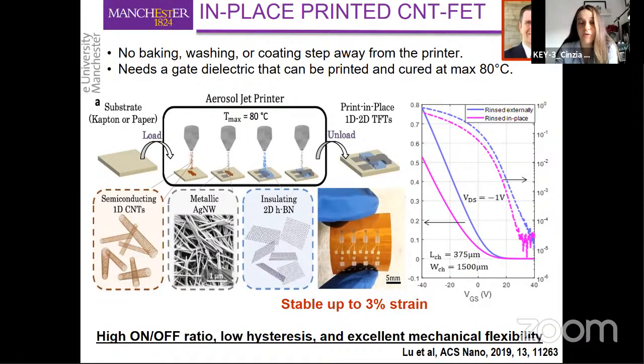And this is enabled by the use of materials that have very good performance even under such a low processing temperature. And this was a problem in the past for Aaron. He tried different types of dielectric materials, and they were always failing every time he was trying to produce the device in these limited conditions. But our boron nitride, in combination with the semiconducting carbon nanotubes and metallic nanowires, demonstrated the ability to produce very high performance devices at a maximum temperature of 80 degrees C.